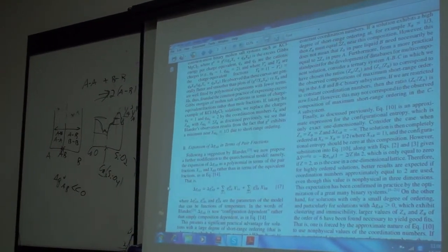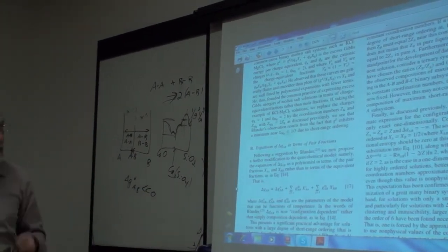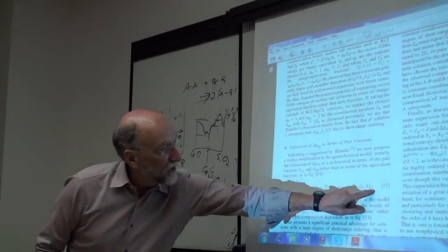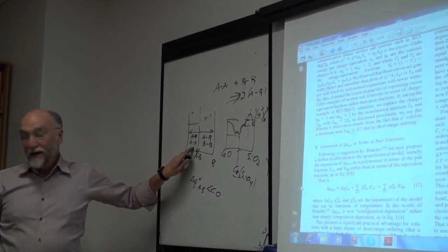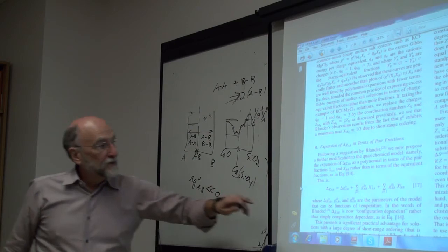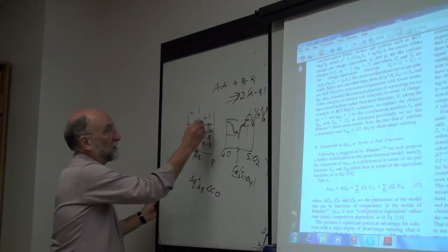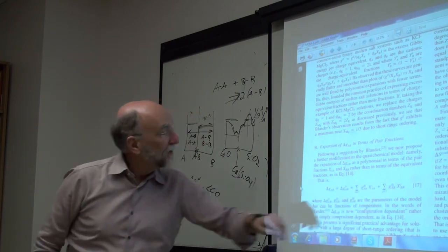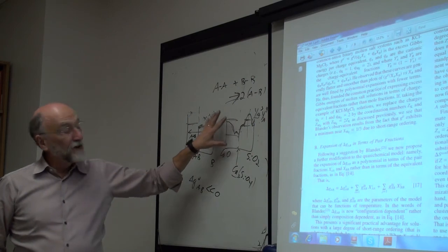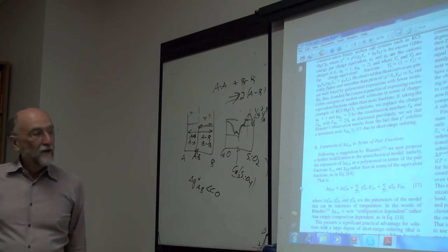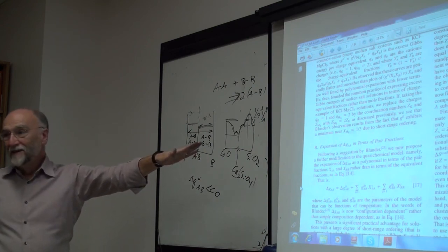However, in this expression, you see that over on this side, this term here takes account of only the XBB pairs. So a term here, this G naught J XBB to the J, will have very little effect on this side because there are hardly any XBB pairs. XBB is extremely small over here. So this second term will have an effect only on this half of the phase diagram. So you can play with these parameters to make your phase diagram fit on this side and have very little effect over here, and vice versa on the other side. And you'll find it's a lot easier to fit using this.